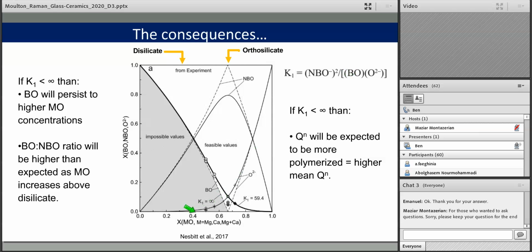The reason why this has been controversial in the past, though it's not so much anymore, is that for this range of silica contents, below 50% of modifier added, so at higher than 50% concentrations of silica, the concentration of this is essentially 0. It's only 1 or 2, maybe 3%, depending on exactly how reactive you want to consider your system. So there are very few techniques that are sensitive to the 1 or 2% level of this feature. But this can lead to very inconsistent interpretations in terms of the proportion of MBO to BO in your melt.